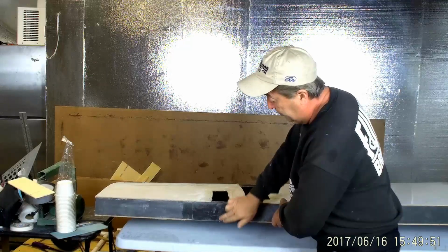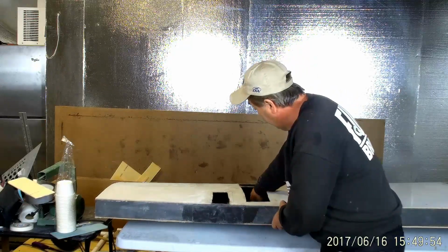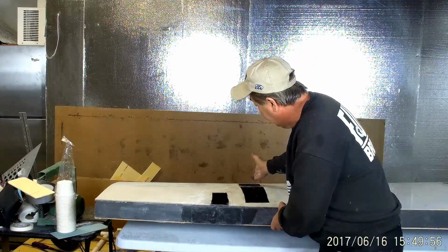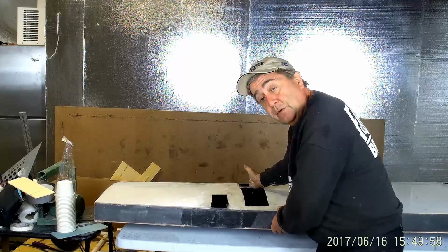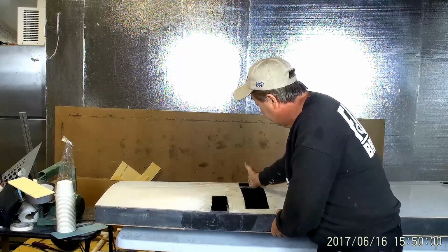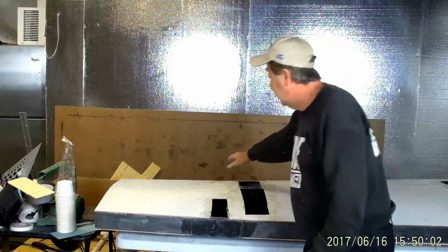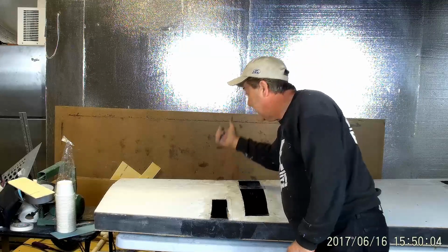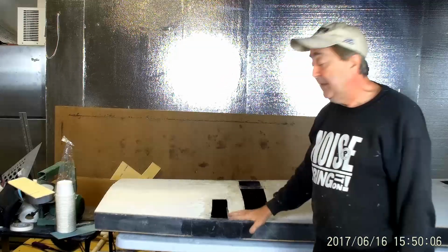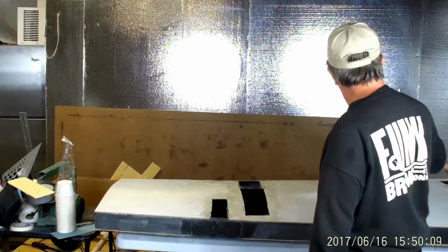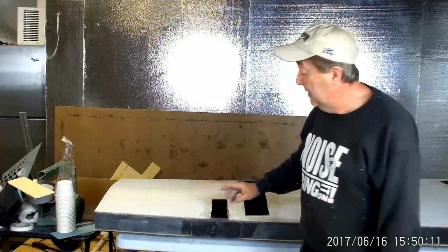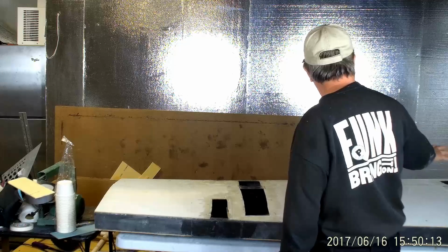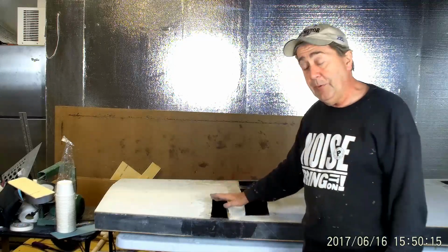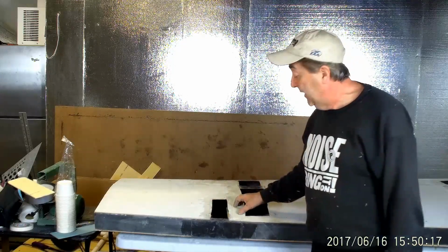The rear spar was broken here, and the main spar's shear web was cracked here, and this spar cap, which is on the lower surface of the wing, was broken in half. And the leading edge is significantly bent and damaged. So fairly significant damage. If you can see the root end, it's all cut open down there. Need not worry about that. I'm changing the design, and I've cut that open for change purposes. Really wasn't damaged at that end.